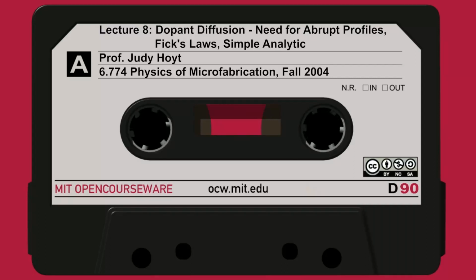And the x-axis is in units of diffusion distance, so the units are 2 times the square root of Dt0. And you can see in going from the red to the blue curve, indeed the concentration has dropped by 1 over the square root of t, because basically the blue curve is for time 4 times t0. So it's dropped by a factor of 2, and it's broadened. And same thing by looking at the green curve, you see the same type of phenomenon.